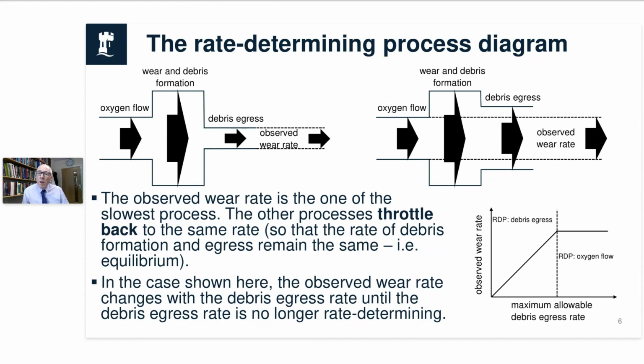So in this case, you can do what you like now with the debris egress. It can get bigger and bigger, and you won't see any change. And that's why in the bottom right corner, we've got the observed wear rate increasing with the maximum allowable debris egress rate, and then stifling because actually now it's controlled by the oxygen flow into the contact. So that's why sometimes we see rather odd effects within our systems, because we need to be thinking about all of those processes, which one is rate determining.